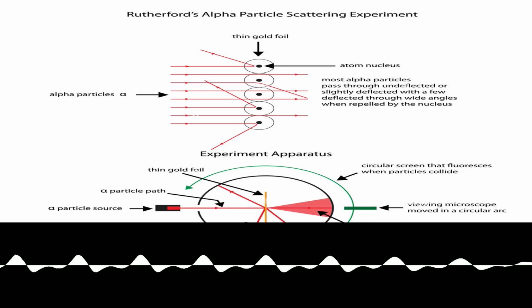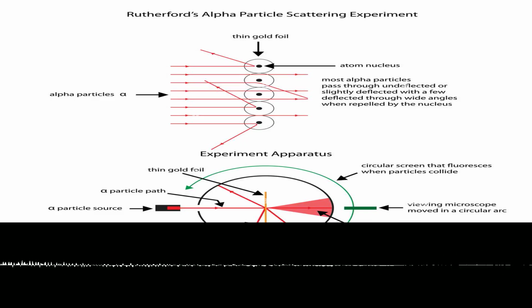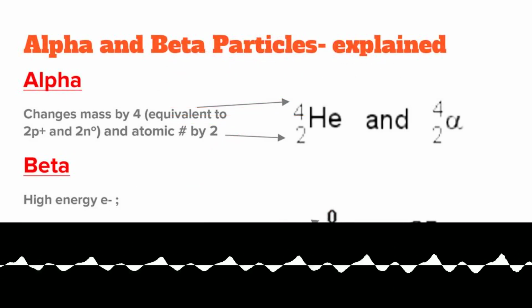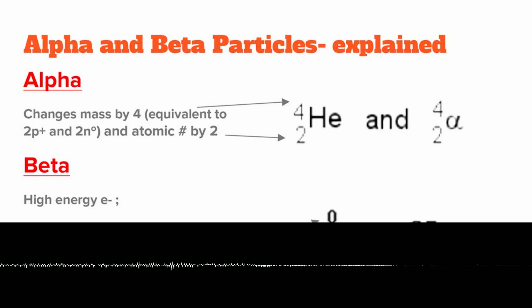Even beyond its role in catalyzing quantum theory and founding nuclear physics, the core principles of the 1911 paper retain a striking modern utility. The physics of particle scattering from a central potential is the direct foundation for a powerful materials science technique known as Rutherford backscattering spectrometry, or RBS. In this application, a beam of light ions, typically helium, is directed at a sample material. By measuring the energy and angle of the backscattered ions, scientists can precisely determine the composition and thickness of thin films, identify elemental profiles as a function of depth, and analyze crystalline structures.